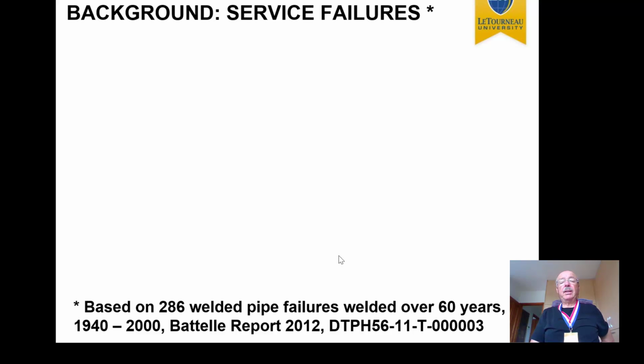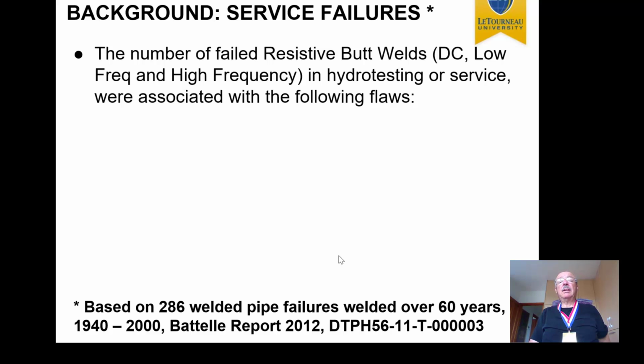Now we looked at service failures to see what is the panic about these bond lines. People keep reporting that they are afraid of them. So we reviewed a very extensive report by Battelle, which reviewed 286 welded pipe failures over a 60-year span. What they found was a really big mix of resistance butt welds, even back to the years when they used DC current or low frequency current to heat up the edges.